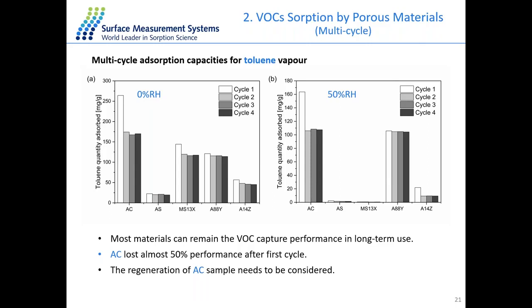The last experiment we performed in this study is we exposed the porous material to multiple cycles of the organic vapors at two different conditions, dry condition and also 50% RH. Most of the materials, the other four on the right-hand side, are very similar in different cycles. But in the case of the activated carbon, the first cycle, which is the white bar, is quite different from the other ones. It has already lost almost half of the performance at both conditions after the first cycle, which might be due to some VOC molecules irreversibly bonding with the chemical sites in the charcoal structure. So it can absorb a smaller amount of VOC molecules in the next cycle.